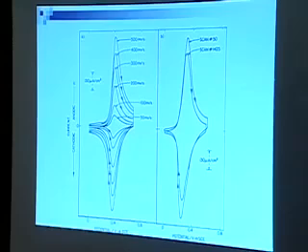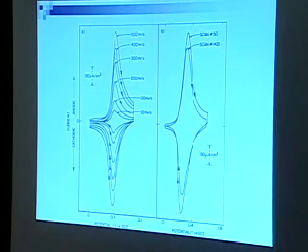I can take cyclic voltammograms of the system, nickel ferricyanide on nickel. First, we just did a whole bunch of them. There's scan 1425 versus scan 50, and to show at 100 millivolts a second that it's a pretty stable system. A nickel electrode itself lasts for about 10 scans. By that point, it's got so much oxide on the surface that it's passivated. No current can flow. We have a little drop-off after 1,400 scans, but it's not bad. We have stabilized the system, practically speaking.